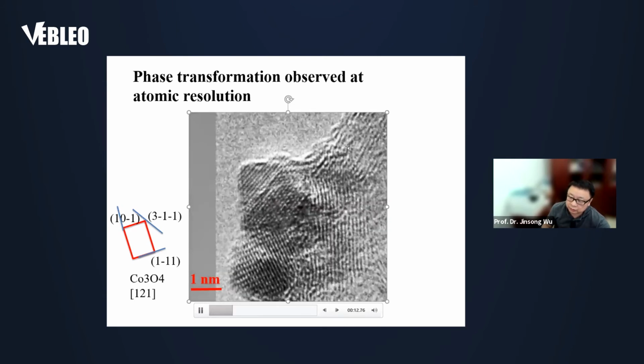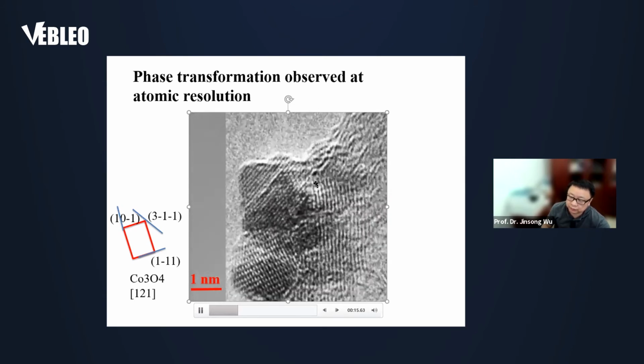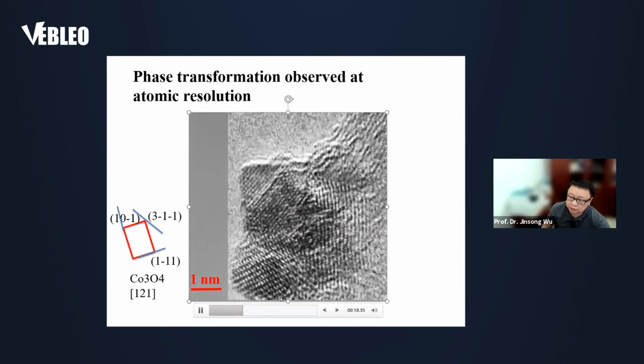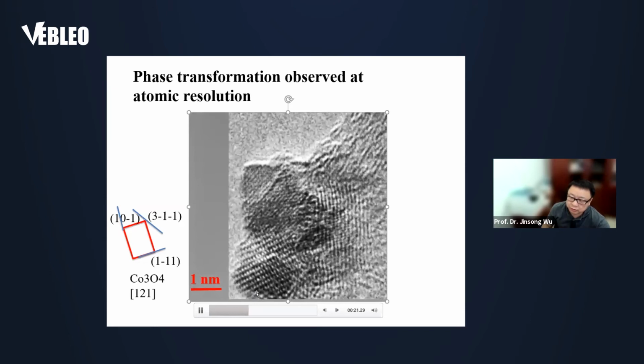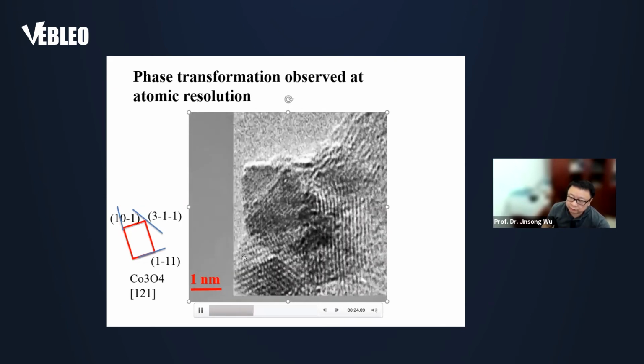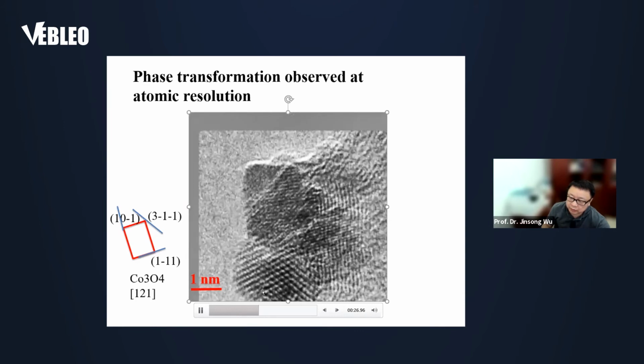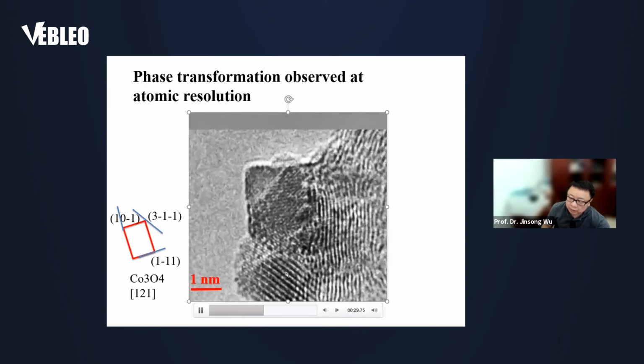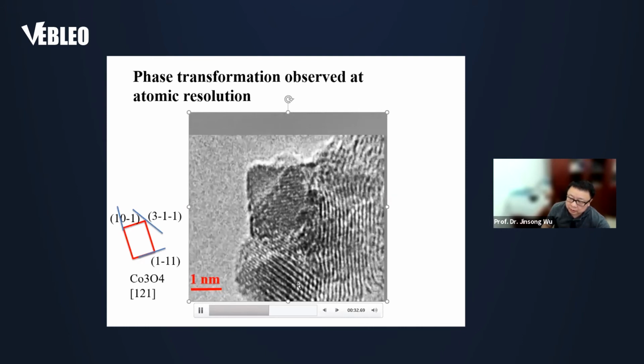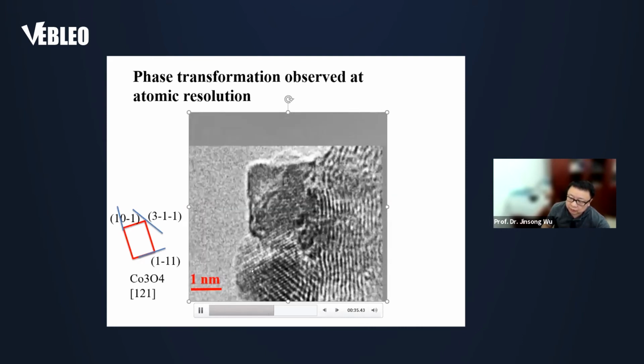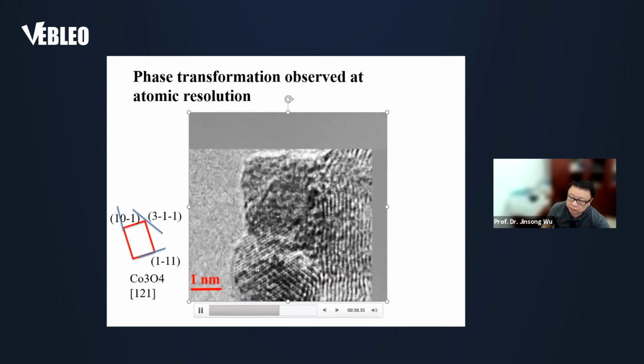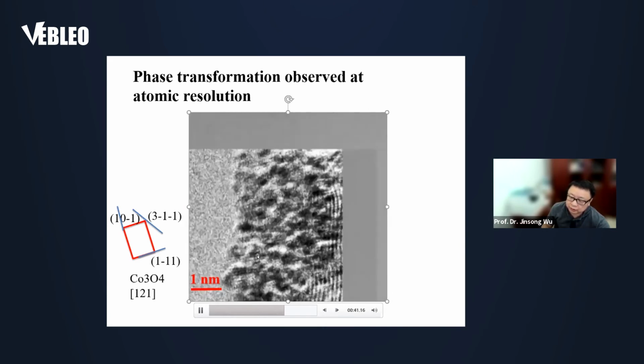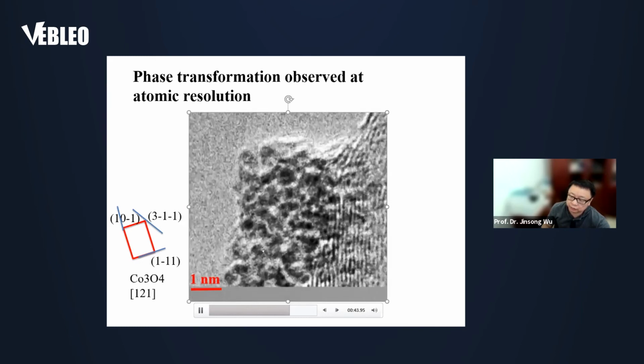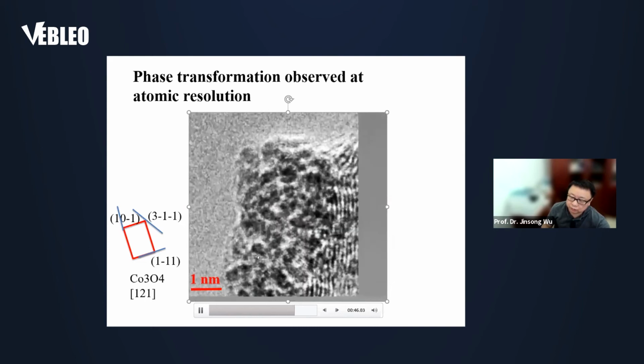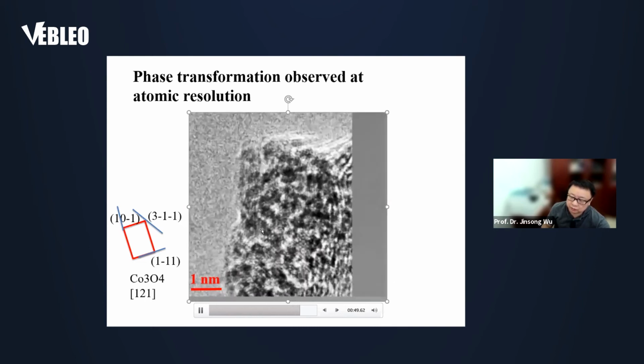And when the lithium comes in, when we did the lithiation, you can see the nanoparticle gradually becomes larger. And then gradually we start to see a very strong contrast of the 311 lattice plane. And here's the 111 lattice plane. And a little later, if you look carefully, we start to see the 111 lattice plane expanding, and eventually it becomes metal particles, which we can identify as cobalt metal particles embedded inside the lithium oxide.